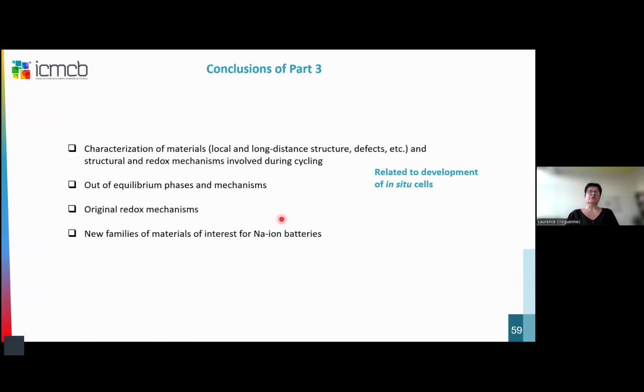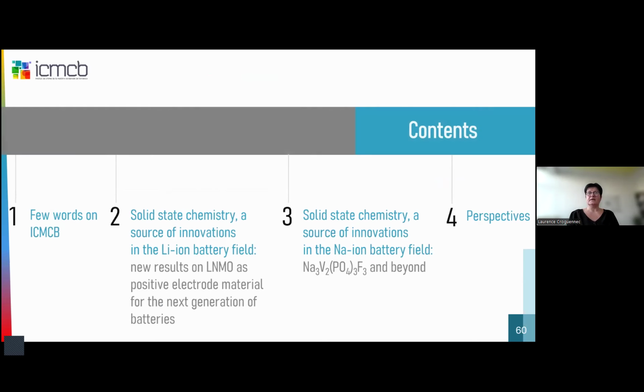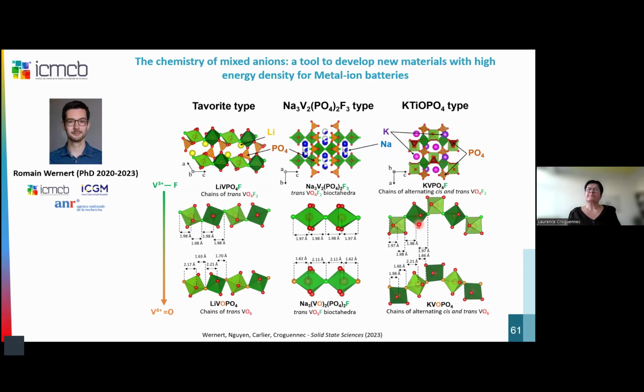So I wanted to conclude this part by highlighting that it's only the in-depth characterization of the materials, I would say from the local to the long-range structures and knowledge of defects, that allows you to understand the materials. We also have a lot of non-equilibrium phases and mechanisms that are observed. And so for that, we need the development of in situ cells. And we are really still able to identify original mechanisms and new families of materials of interest for sodium-ion batteries. And I will conclude my talk by giving two perspectives.